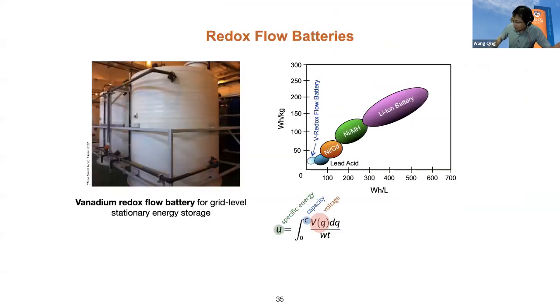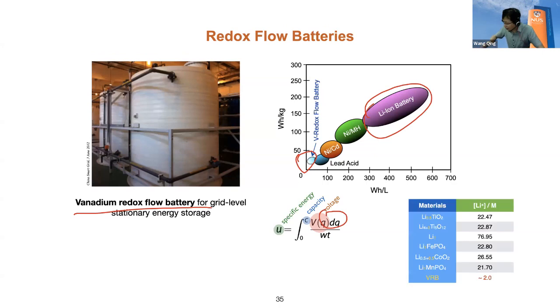For energy storage, as I said, in the conventional flow battery, like a vanadium flow battery, we store the energy in a vanadium solution. If you look at the energy density compared with the lithium battery, it's one order of magnitude lower. It's mainly because the concentration of vanadium species is low. The concentration is just 2 molar. And in lithium battery material, the effective concentration of charge is typically about 20 molar. That means one order of magnitude higher, without considering the voltage difference.